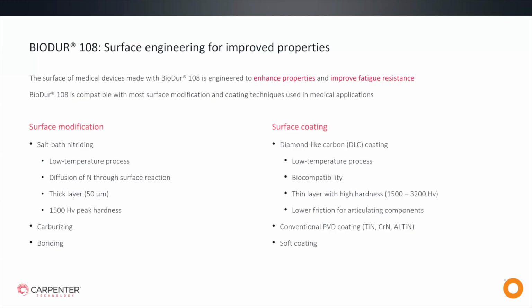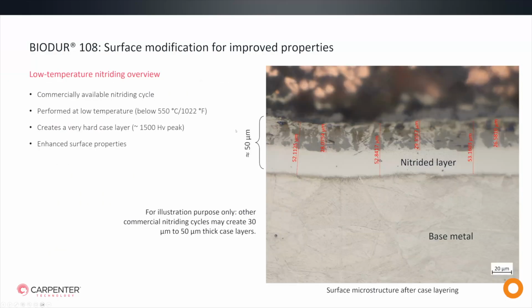However, it does show the compatibility of the material in diffusion hardening, such as salt bath nitriding, carburizing, boriding, or a combination thereof. Or on the right-hand side, surface coatings, like diamond-like coating, the DLC, for very low friction and also an incredibly high hardness. So these processes are somewhat standard, somewhat commonplace in the medical industry. We see them being used. And it really just makes BioDur 108 another option that is practical, that is scalable, and has potential as an articulating device material replacement.